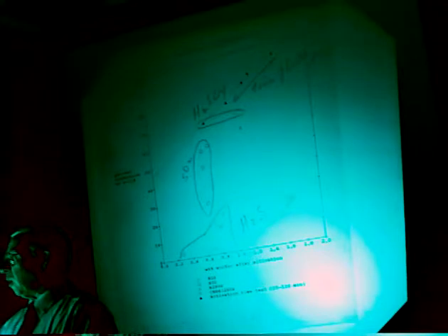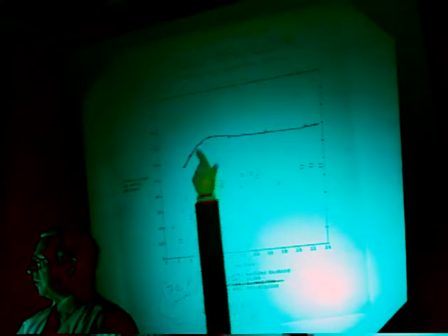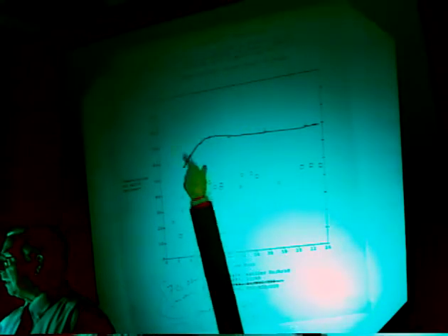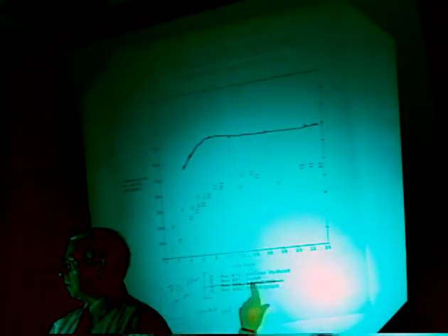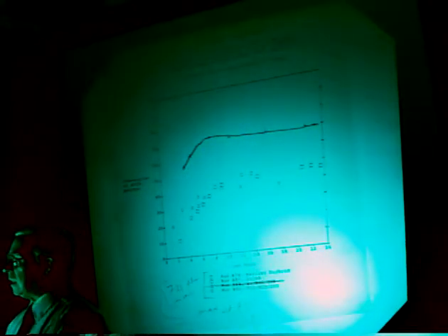SO2 is shown lower here, but it is difficult in our hands to reproduce the SO2 addition, and so here you see in a plug flow reactor, or a trickle bed reactor rather, when it's made from the SO2 and then oxidized, we get the highest activity.